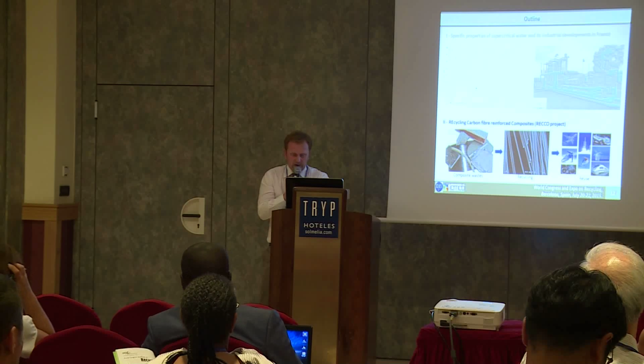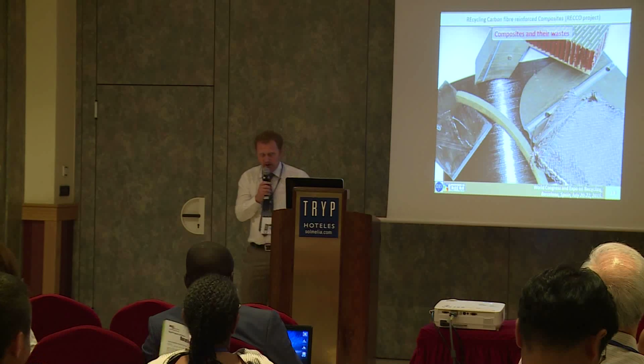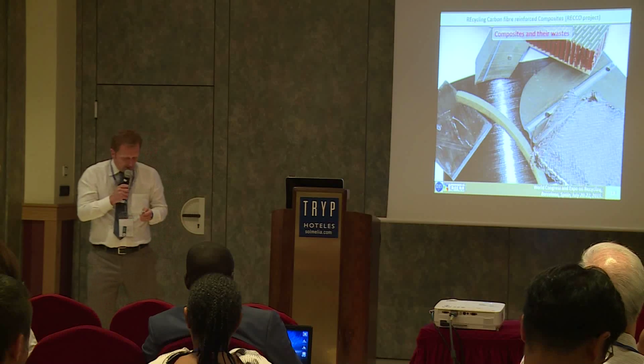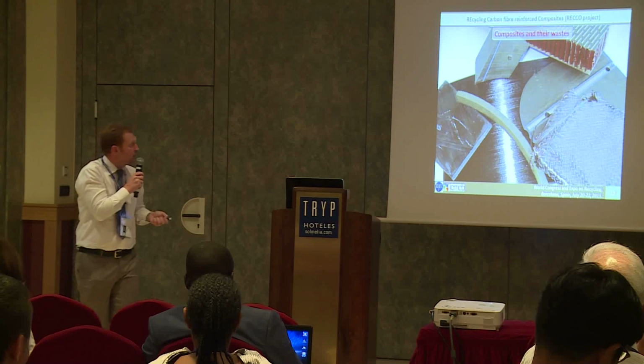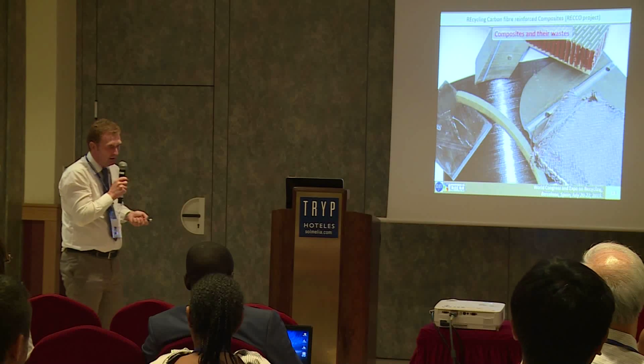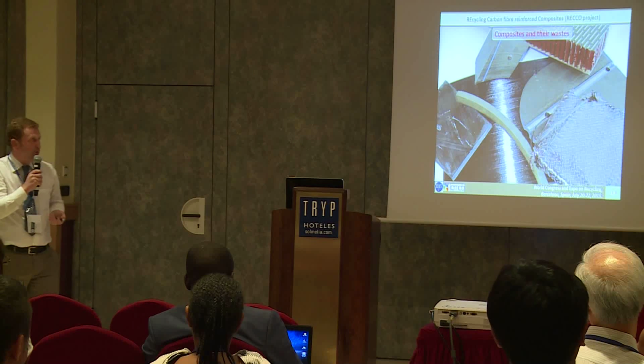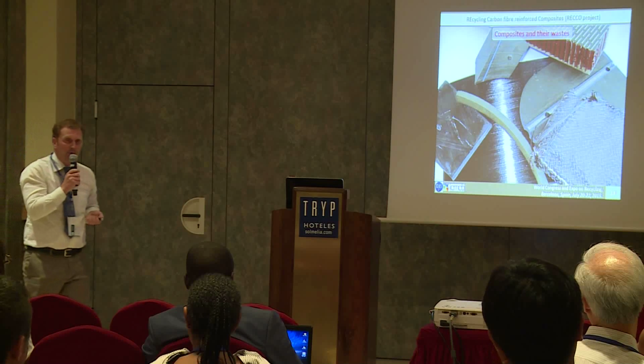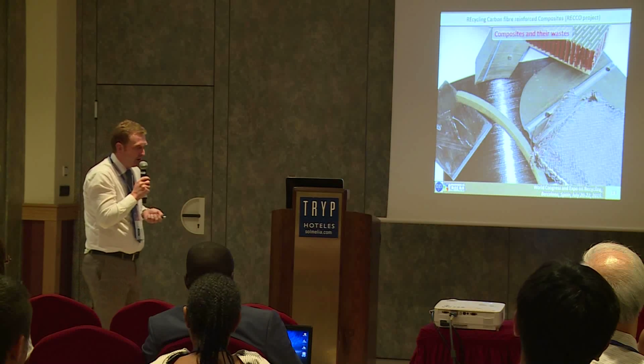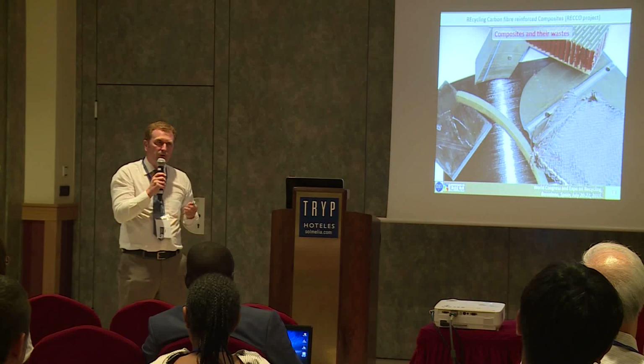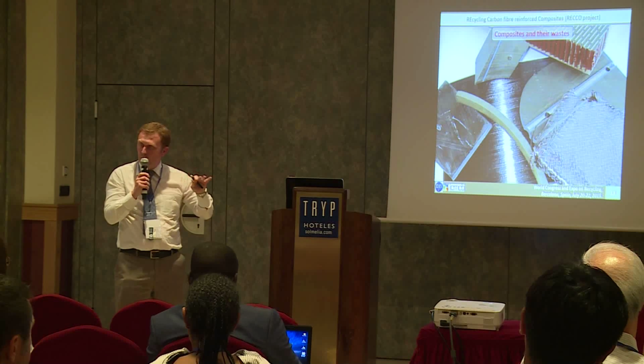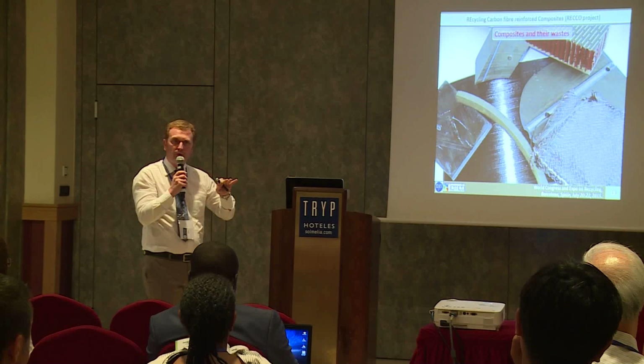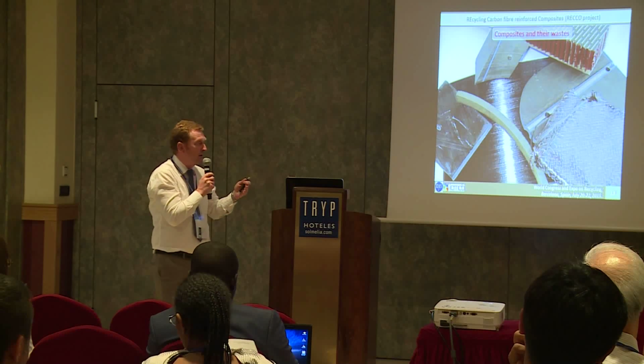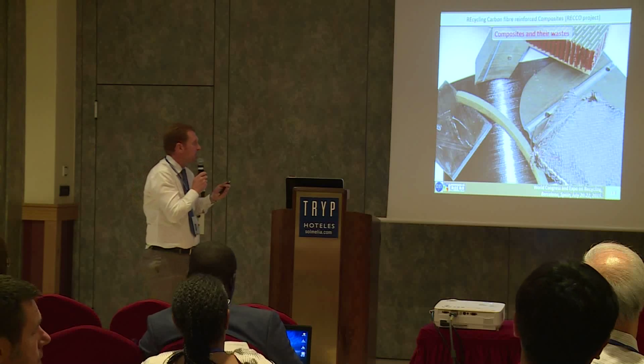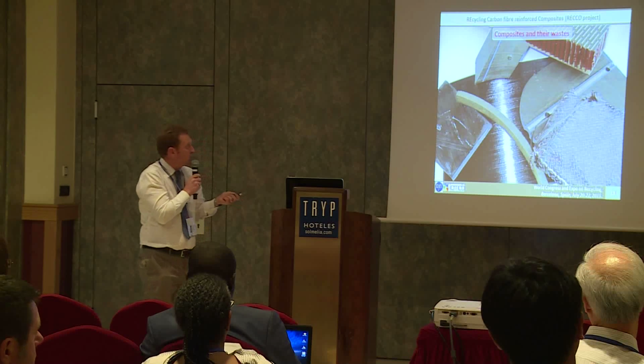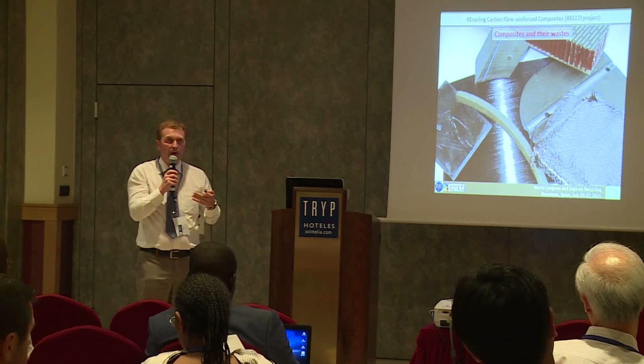And this is an important point because this company can support our technological development in the field of the recycling of composite materials. So we came to this about in 2008 when the Airbus plane manufacturer came to the lab and said, could you do something to help us? And in fact, they came because we made some tests in 2000 on just epoxy resin. And we showed at that time that it was possible to solubilize, to hydrolyze very easily some epoxy resin in supercritical water. And they said, okay, but we need to work on a real waste.